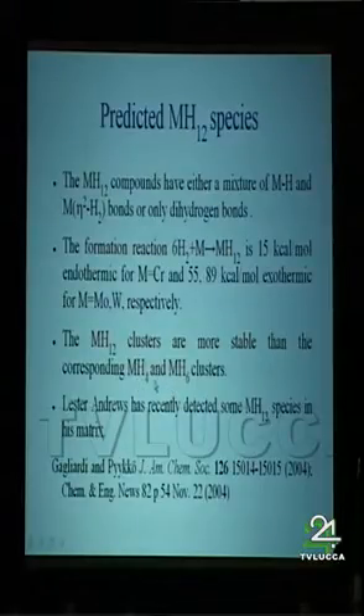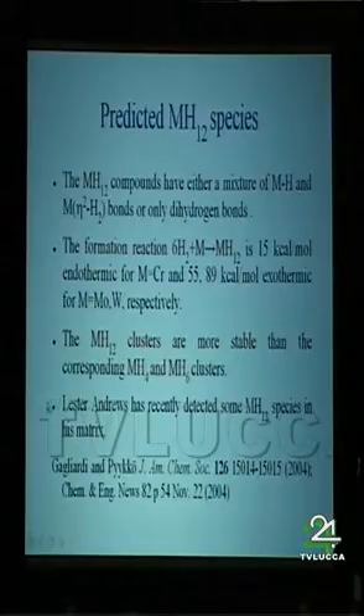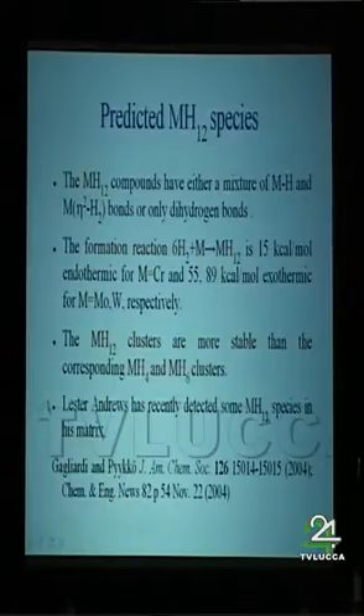And chromium H12 had been seen in the matrix by the group of Lester Andrews in Virginia. And actually, when we first published the paper, he said, we couldn't see your chromium H12, so how can it exist? But then he went back to his experiment on the basis of our calculations, and he could see the frequencies of the larger clusters based on our predictions. So this is to show you how sometimes theoretical work can also help experimentalists in their measurements.